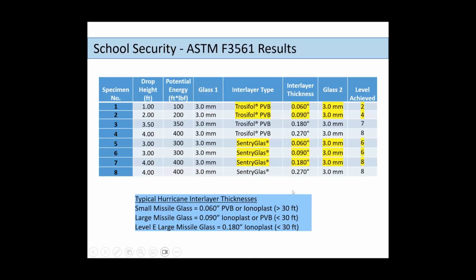So we've done a lot of testing for this with different interlayers. In the testing for school security, there's 8 levels. Level 1 is the lowest level, Level 8 is the highest. What we found was that, in general, the thicker the interlayer, the better the performance. And also, the ionoplast performs better than the PVB. So, for example, if you were going to use the ionoplast with a 90 mil large missile level D with 3 millimeter glass, you would achieve a level of 6. But with PVB, for the same thickness, you'd only be at 4.